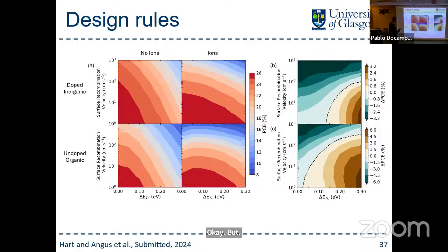So if you look at a device without ions, we can make basically a 26% cell all the way up here, whereas this kicks in soon. So it's a trade-off. With solar cells with ions, you don't have to optimize the energy offset of your contacts so much, but you need to be very careful with your surface recombination.